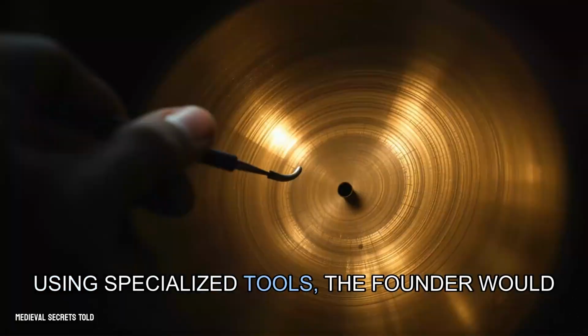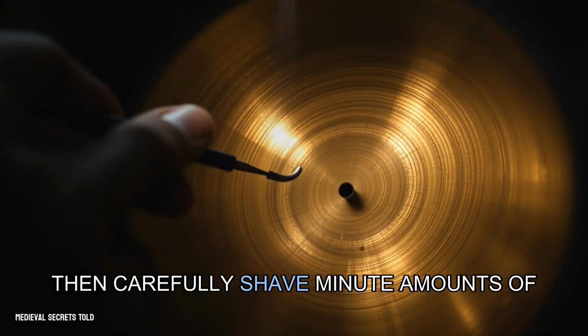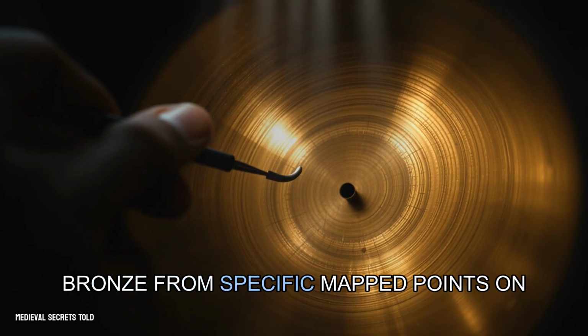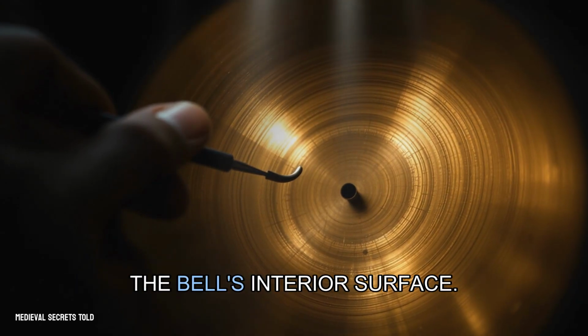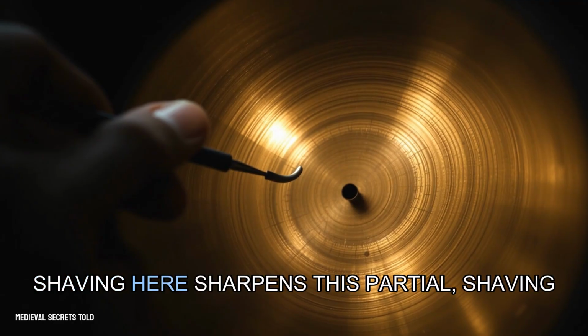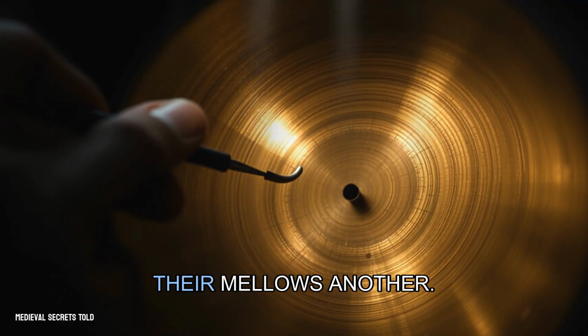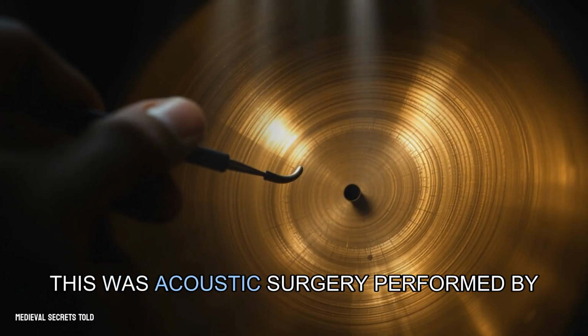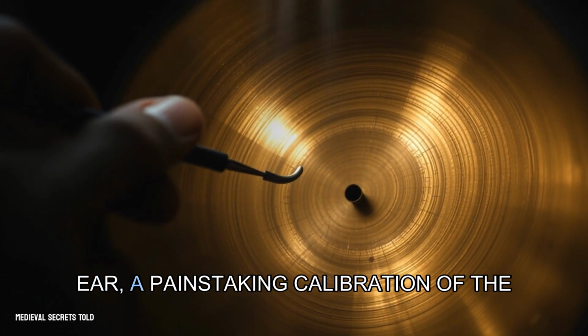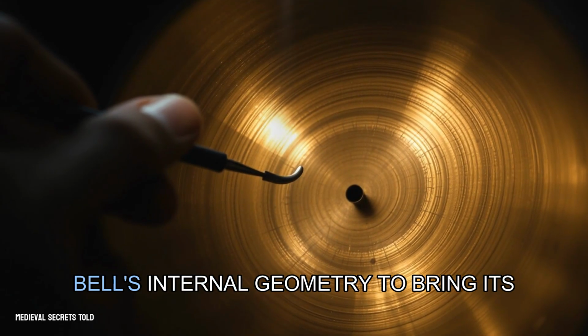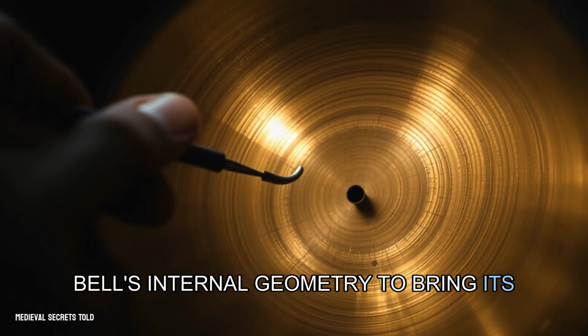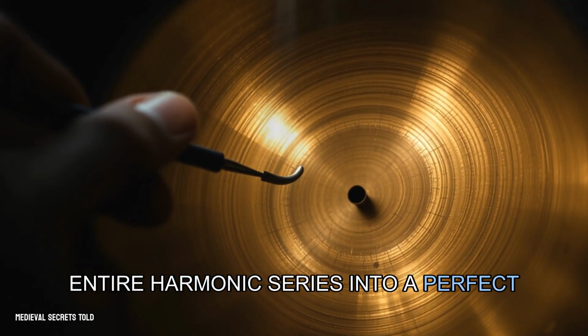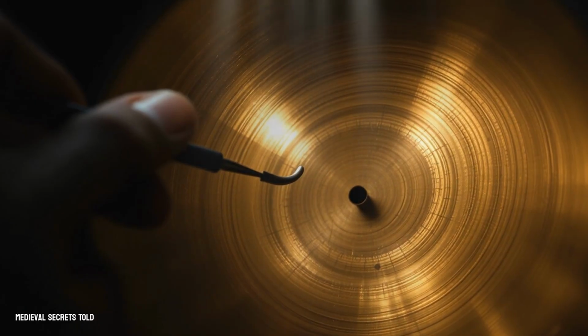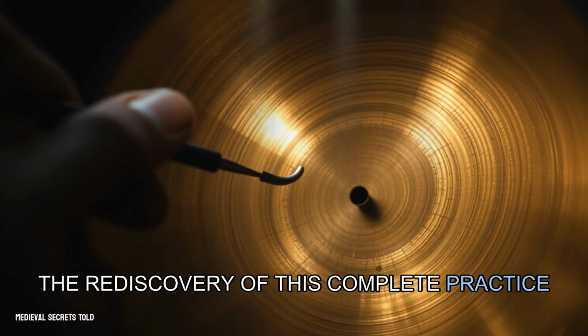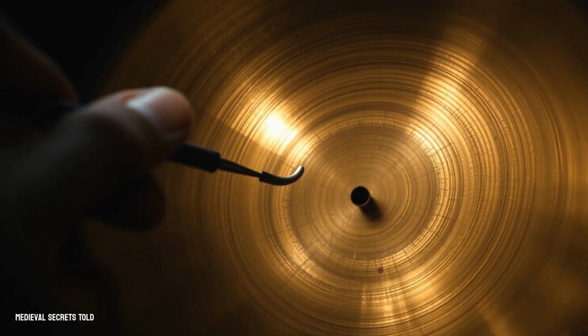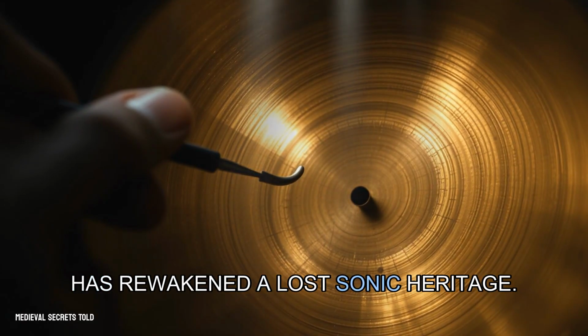Using specialized tools, the founder would then carefully shave minute amounts of bronze from specific, mapped points on the bell's interior surface. Shaving here sharpens this partial, shaving there mellows another. This was acoustic surgery performed by ear, a painstaking calibration of the bell's internal geometry to bring its entire harmonic series into a perfect, resonant alignment. The rediscovery of this complete practice, from alloy to final tuning scrape, has reawakened a lost sonic heritage.